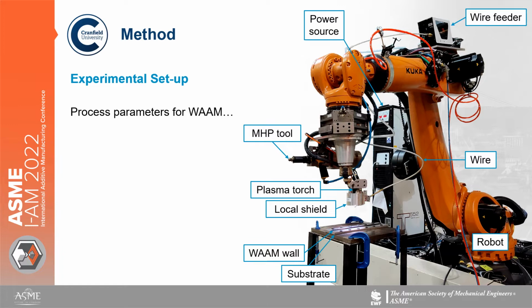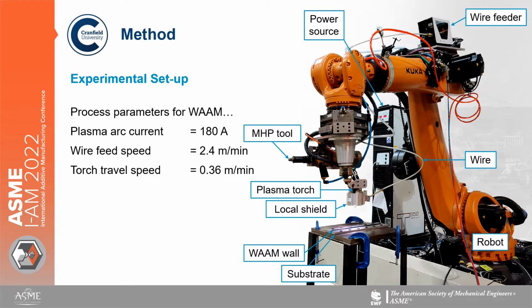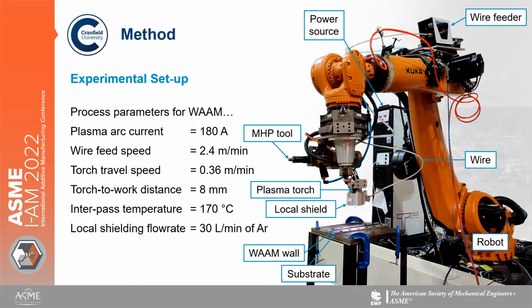So here are our process parameters for our additive manufacturing. So we used a plasma arc current of 180 amps, a wire feed speed of 2.4 meters per minute, torch travel speed of 0.36 meters per minute, a torch to work distance of 8 millimeters, and we used an interpass temperature of 170 degrees Celsius, which was an approximate temperature after about 3 minutes of cooling. And the local shielding flow rate, which is the flow rate of shielding that went into the local shield, is 30 litres per minute of argon.